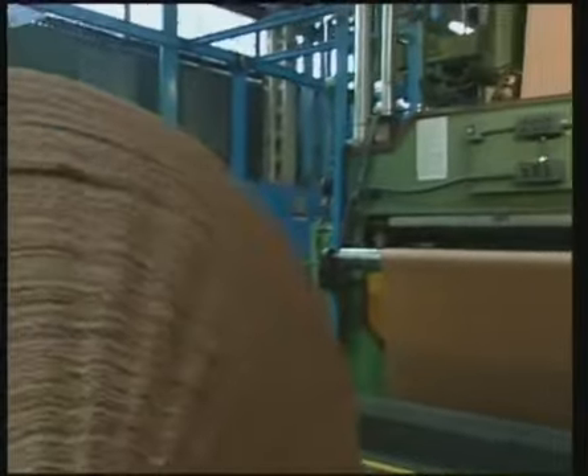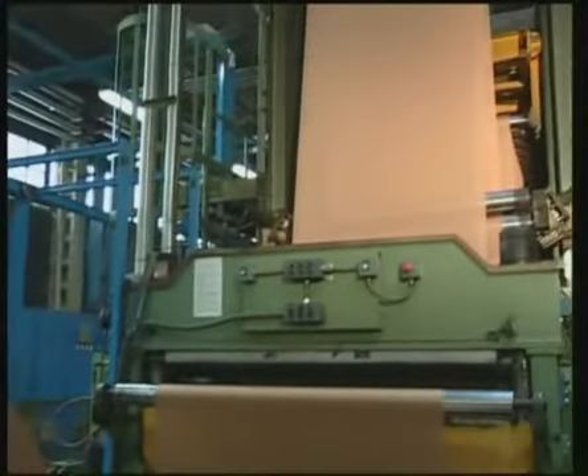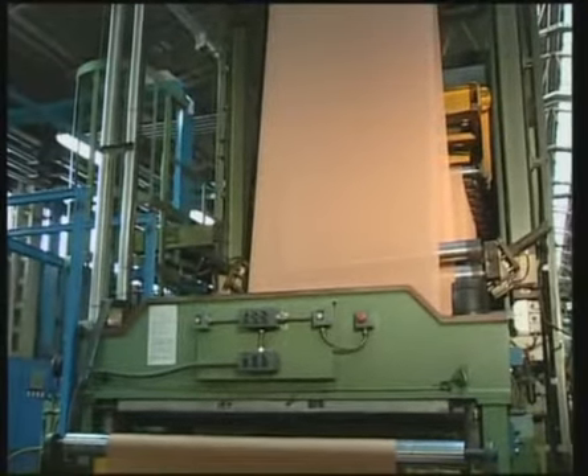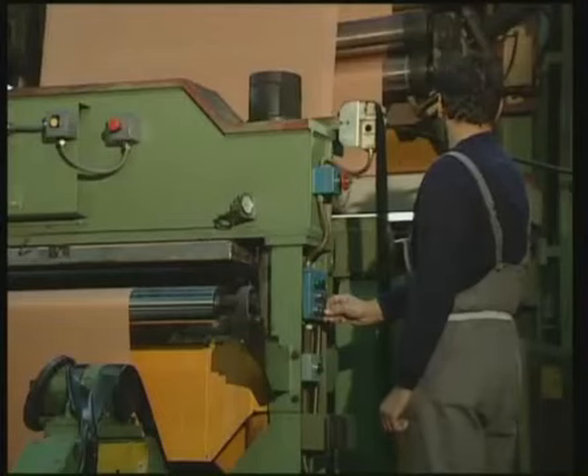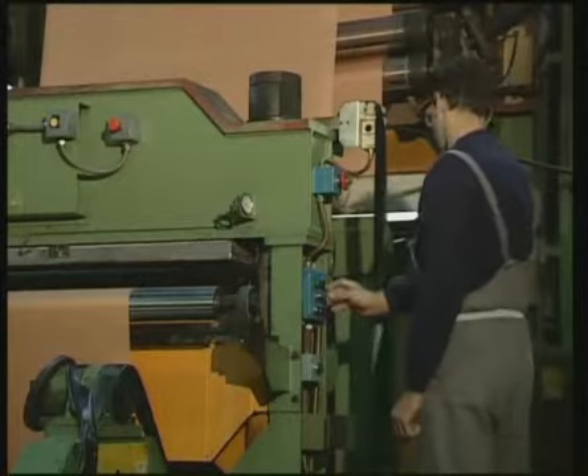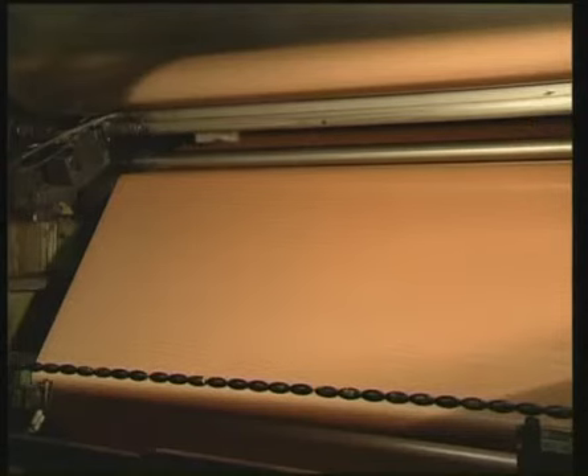The fabric supplied on large reels has previously been specially treated by the supplier to increase its adhesion to rubber. Yet that's not all. Before coming into contact with the compound designed especially for this purpose, the fabric must pass through some elements of the machine so that the correct tension is applied. And any residual moisture that may affect perfect adhesion to the rubber is removed.